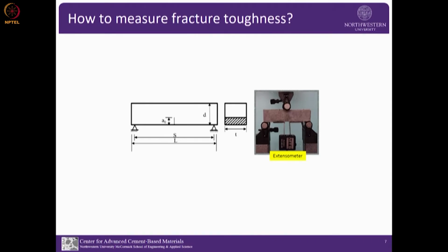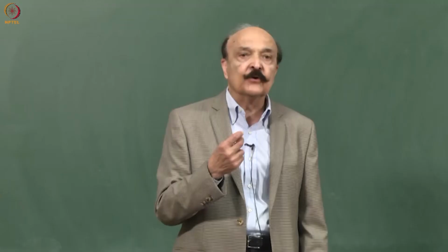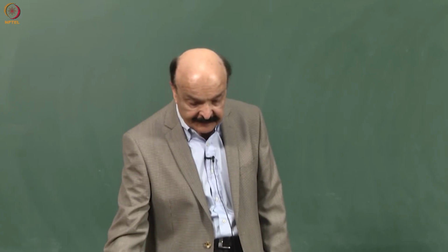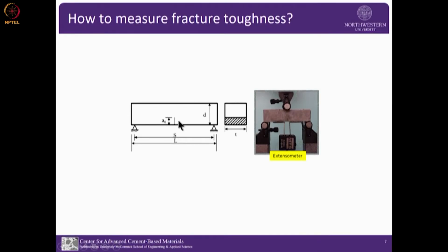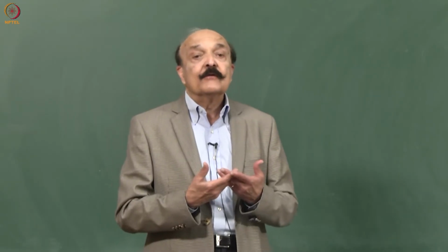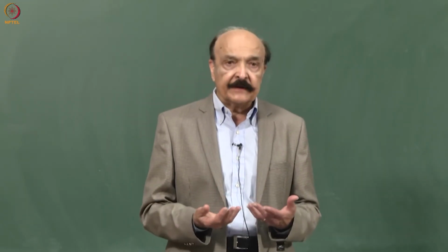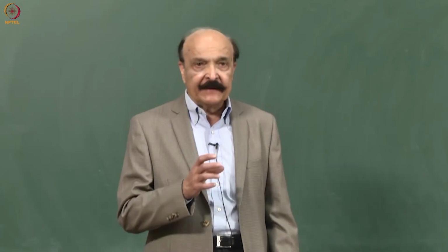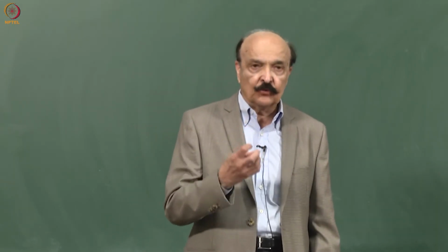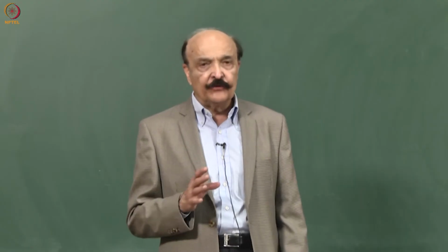Well, for linear elastic fracture mechanics, there are ASTM tests. You have a notched beam, and you apply the flexural load, and when it reaches maximum, everything is elastic. From the peak load and the crack depth, you can calculate fracture toughness. But a lot of work has been done, and it turns out that concrete is not quite brittle; we call it quasi-brittle. In crack propagation before the peak, there is a so-called fracture process zone. So you cannot use LEFM.